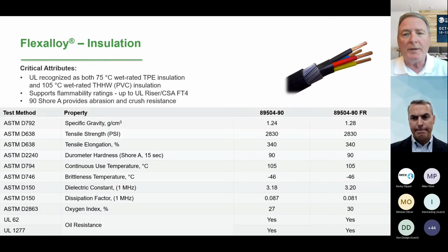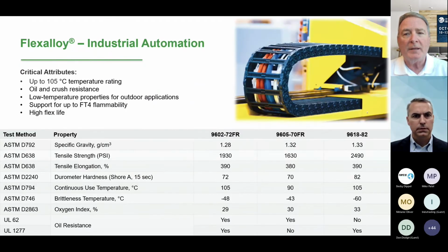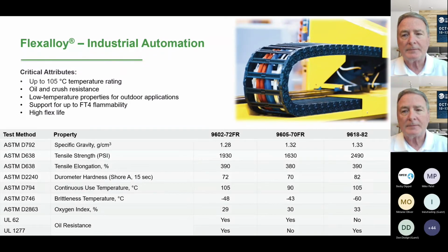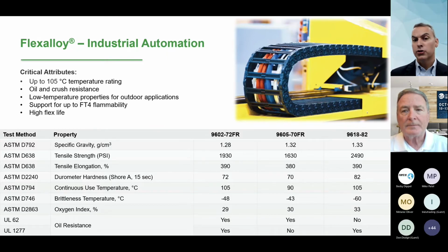Good. Would the 9602 72 FR be a good choice for a TC-ER rated FT4 with VW1 XHHW conductors? So as long as the XHHW is VW1, it may be a good choice. We would want to talk about the specifics of the number of conductors, the conductor size, how sometimes when you go to smaller conductors, it becomes more challenging to pass the burn. In some cases, we might recommend stepping up to the 9605 or the 9618. And we do have some other jacket compounds that have even higher LOI and they give up a little bit on the brittleness temperature. But as far as the TC and the ER, yes, these are good choices.